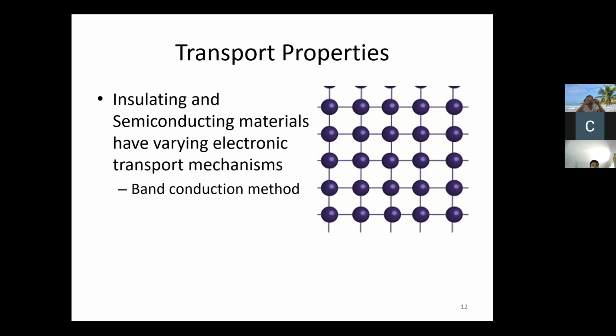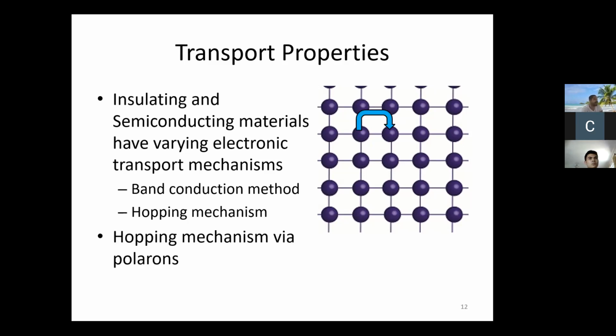And so that's where we typically have the bands, and you say, oh, you can add electrons to the bands, and then you have an effective mass, and that's what we're generally looking at. But there's also this other mechanism in insulators, which is a hopping mechanism. So you could have certain sites where electrons or holes can sit on, and they could just hop from one site to another. And they could either hop onto defect sites or just some other sites that can have hopping. And so you can see from this arrow, you hop from one site of a lattice to another.